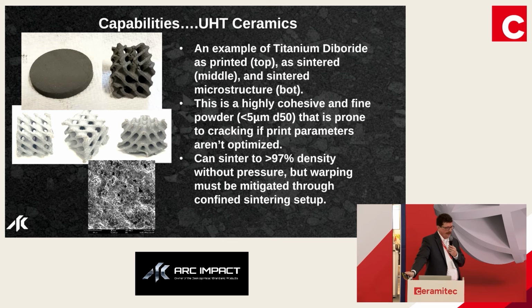Something sort of on the research scale, I had mentioned these UHT ceramics, ultra high temperature, things like diborides for hypersonics. The powders themselves can be a bit tricky to print. They tend to be very cohesive. You need to either add flow aids or a quantity of sintering aids to get them to dispense, but then also densify. But typically flow aids are carbon-containing elements that might not be good for the sintering, and the sintering aids you might have to add in a quantity that you don't want, but gets the job done.